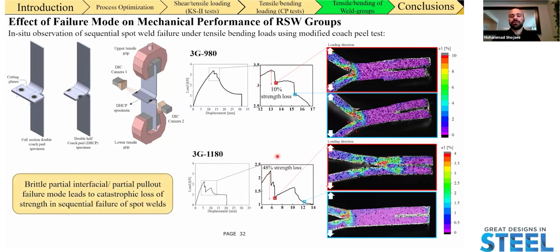So what that really means is that if we get brittle partial interfacial partial pullout failure, which is the case for 3G1180, that definitely affects our load displacement response. That is another reason that we have inferior mechanical performance in the case of the 3G1180. So essentially, we have two parameters that are affecting the mechanical performance of sequential weld failure: the first one being the flange ductility, and the second one being the weld failure behavior.